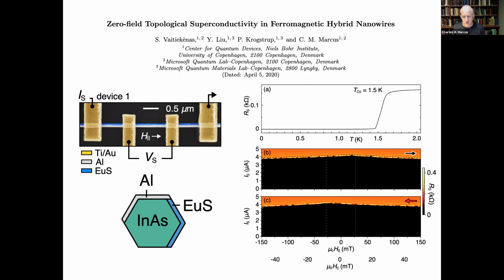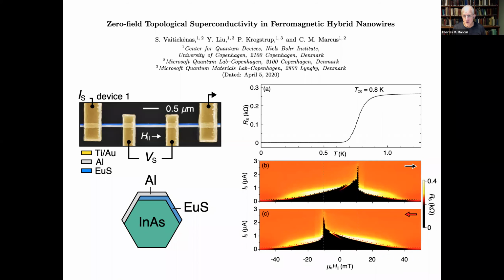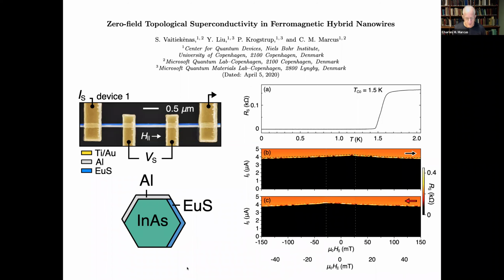And second of all, the critical current, it does have some feature. It does depend a bit on the external magnetic field. And it does have this flip symmetry where it rises and then falls, but it's a very small effect. So if I contrast this with what we saw when the facets overlap, where there's this dramatic feature, with the situation where they don't overlap, where the feature is almost impossible to see, really, and the critical field is higher, one gets the feeling that the overlap between the aluminum and the europium sulfide is where the action happens.